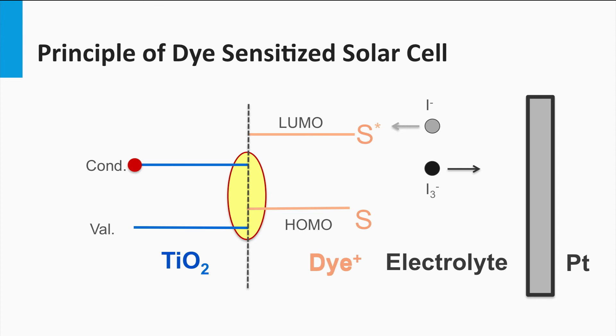Between the counter electrode and the dye, a so-called electrolyte is placed. Electrolytes are solutions or compounds that contain ionized entities that can conduct electricity. Typical electrolyte contains iodine. The positively charged oxidized dye molecule is neutralized by negatively charged iodide. Three negatively charged iodides neutralize two dye molecules and create one negatively charged tri-iodide. This negatively charged tri-iodide moves to the counter electrode where it is reduced using two electrons into three negatively charged iodides.